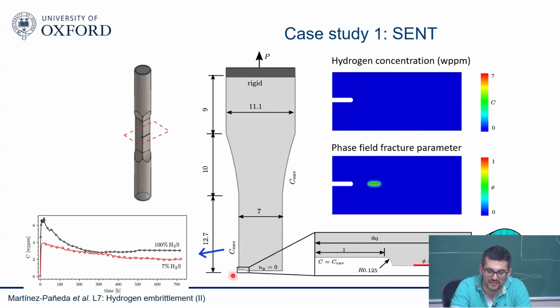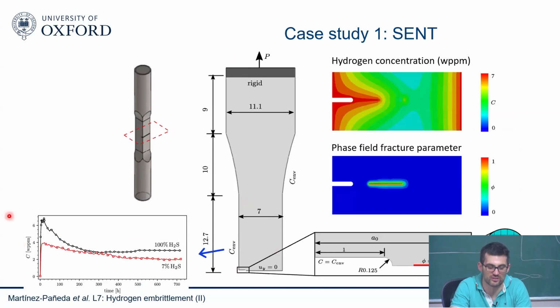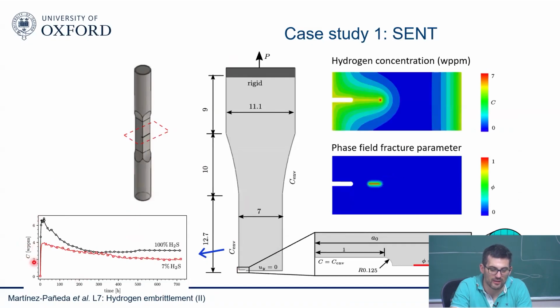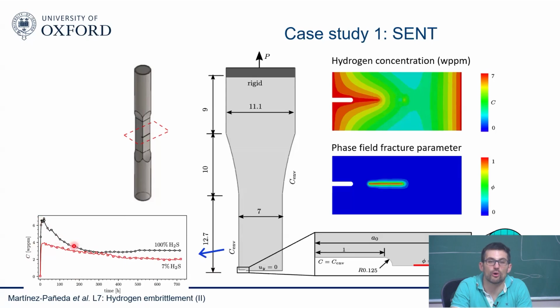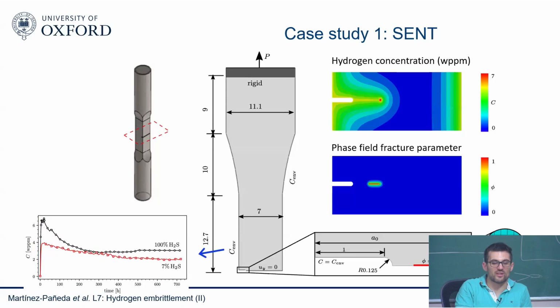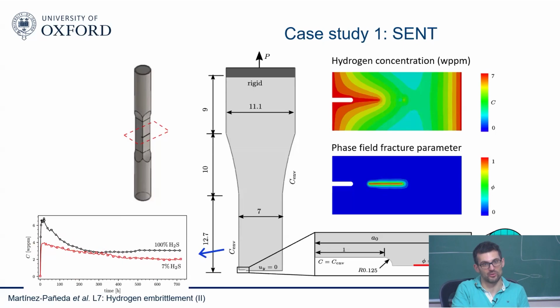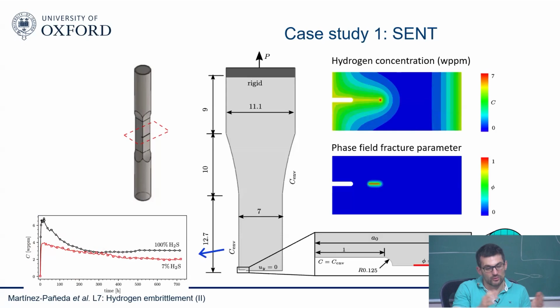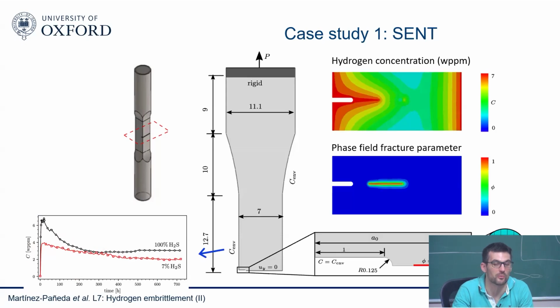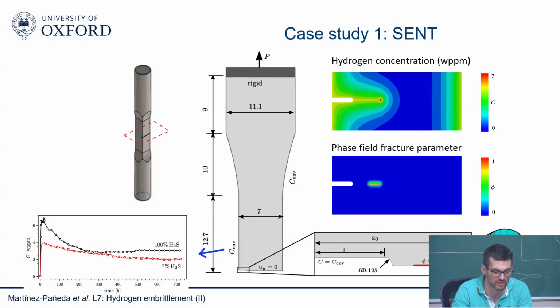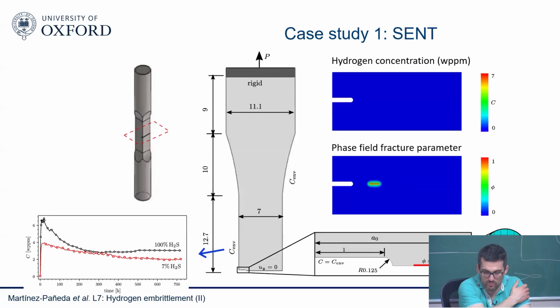And what is important is that the hydrogen concentration that we prescribe on the surface is the one we measure from the permeation test. So you can see here, it goes up initially, but then it goes down. And I mean, we had to take this as an approximation. I think it's the best we could do. One could argue that maybe what you measure in a permeation test is not exactly what you see ahead of a crack, and so there are other things that ideally we'll have to explore. But it's the best we could do with the resources that we had at that time. The H2S phenomena is not fully understood also from an electrochemical perspective, so it was not easy. But there is work to do. If someone gave me infinite resources,